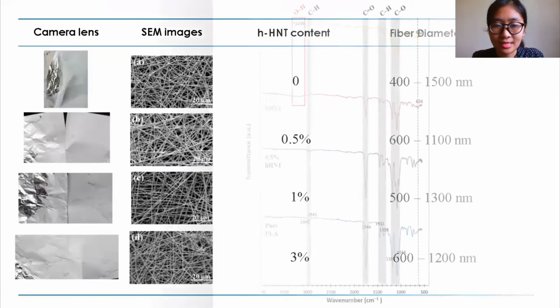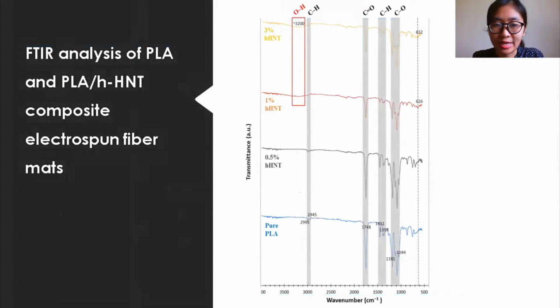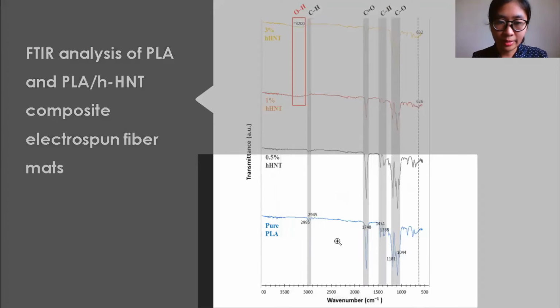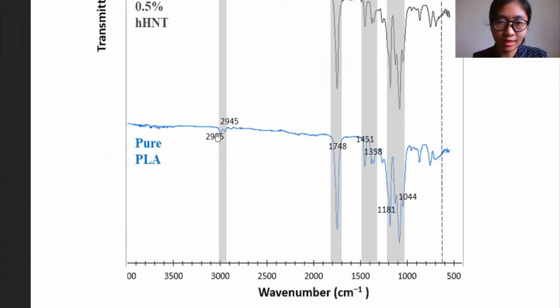So next is the FTIR analysis of PLA and the composite fiber mats. So for the polymer matrix, characteristic peaks at 2995 and 2945 wave numbers can be attributed to a carbon-hydrogen bond stretch, while a strong peak captured at 1748 can be attributed to the carbonyl bond stretch of an ester. The intensity of the signal represents the strong dipole moment associated with the carbonyl of PLA.